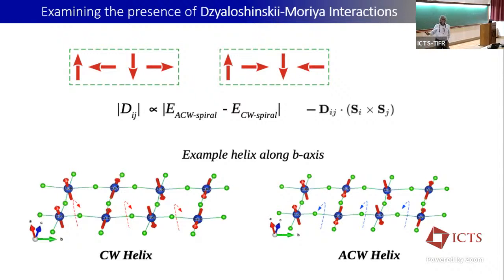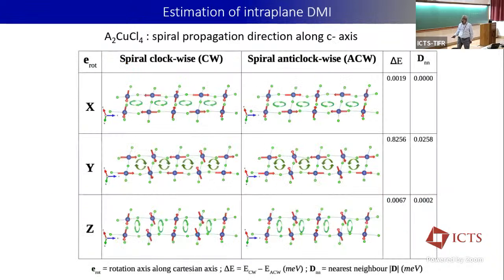So what we did is that we used the chirality of the DMI to calculate the DMI present in our system. Basically, you do a clockwise rotation and an anti-clockwise rotation, and this D is the difference between these two. And we did this calculation. This is the clockwise helix, this is the anti-clockwise helix, and these are the numbers for a representative case. This is for the chlorine system, when you are doing it along the C-axis, and you do clockwise and anti-clockwise, and these are the D values which are calculated. These are the nearest neighbor.